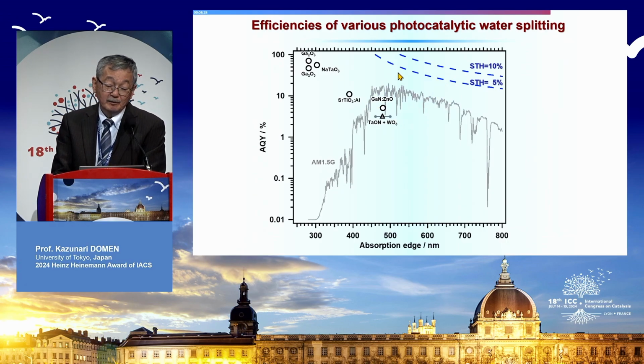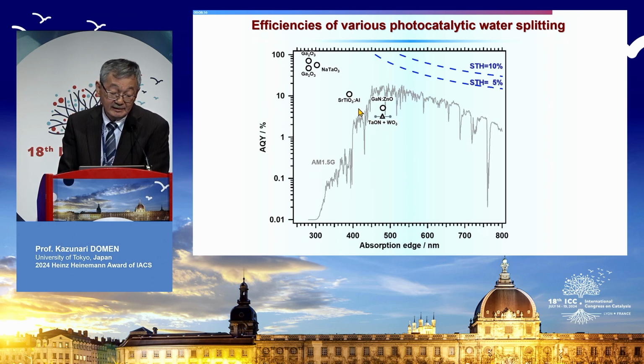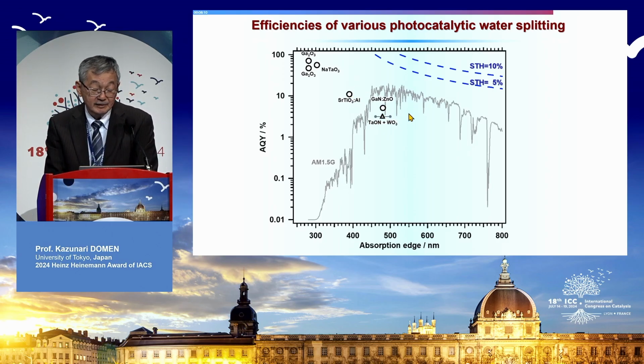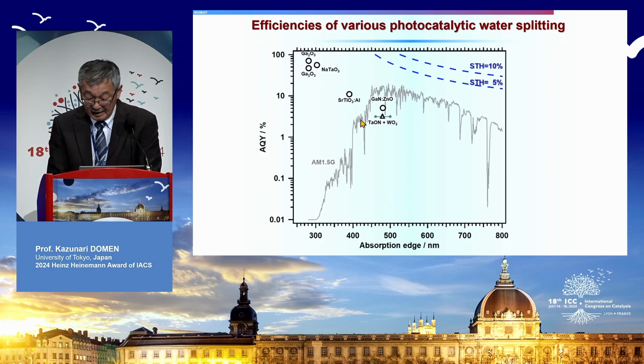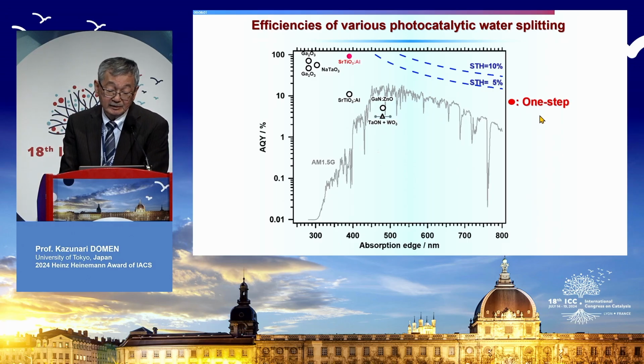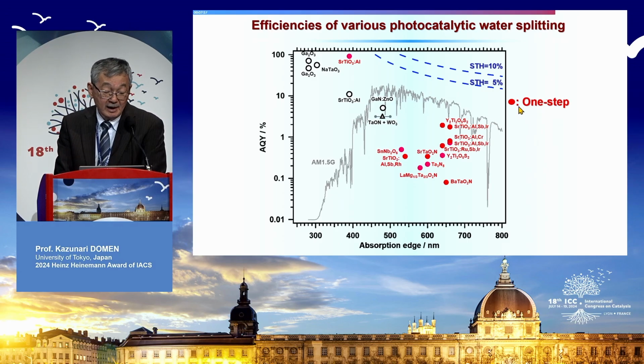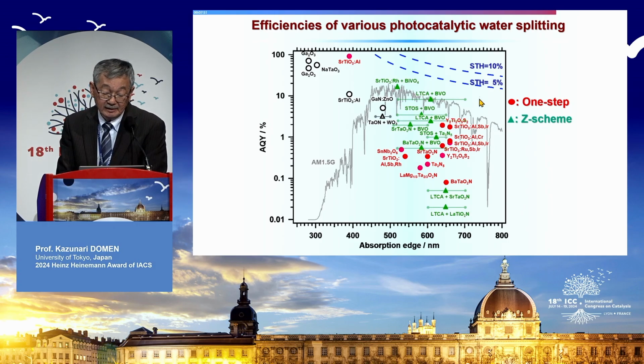Here I show the efficiencies of various photocatalytic water splitting reactions. This is the apparent quantum yield in a logarithmic scale, and this axis shows the absorption edge of our photocatalyst. This circle shows one-step overall water splitting photocatalysts. This triangle shows two-step water splitting systems. And these black ones are actually a little bit old photocatalysts. More recently, for one-step overall water splitting reaction, we have developed these types of photocatalysts. And for the two-step water splitting reaction, we developed these types of photocatalysts. This is not only our group's work, but it includes Professor Kudo's group and Professor Sakata's group of Yamaguchi University.